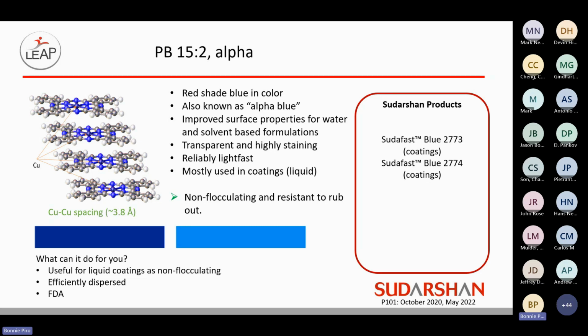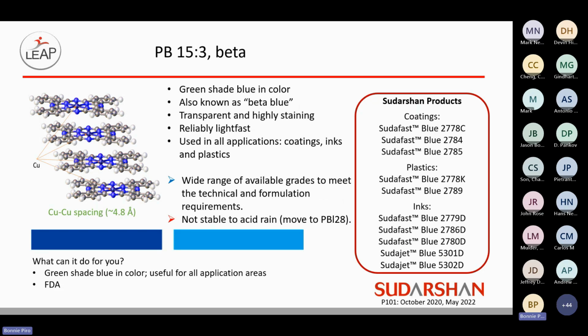The coatings grade, the 15-2, is primarily used in the liquid coating areas to provide non-flocculation and resistance to rub outs. So it's a very useful pigment for the liquid coatings, especially because it does disperse very efficiently. And then shifting to the beta version, which is the green shade in color. Again, very, very useful pigments. There's a wide range of available grades, as you can tell by the number of products Sudarshan offers in all these different areas.